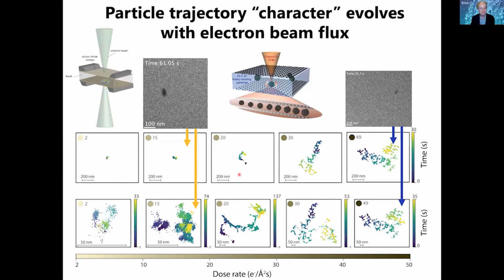Furthermore, if we take each one of these panels and we expand it spatially, not at the same time interval anymore, of course, the time interval will change because the particles move different amounts. The displacements are so different at the different e-beam fluxes. But if we look carefully at this, what we can see is that the particles move in ways that seem to suggest very different patterns of motion. It looks like the mechanism of the motion must be changing as the electron beam is becoming brighter.